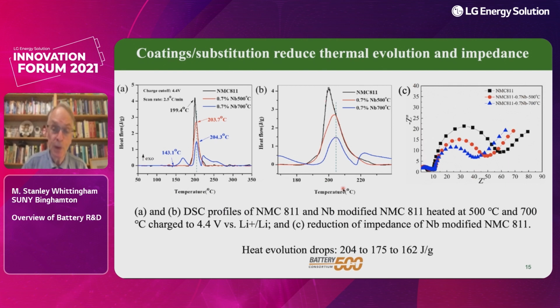From the unsubstituted, it's 204 joules per gram. For the coated, it goes down to 175, and for the substituted, down to 162. So these materials are more thermally stable, and as I said earlier, this is probably a kinetic phenomenon. The ions can't move so rapidly.